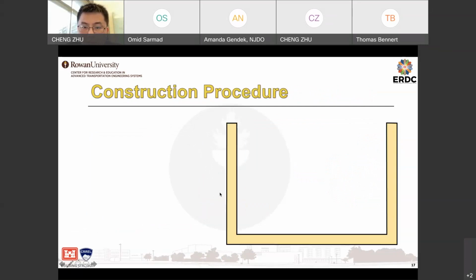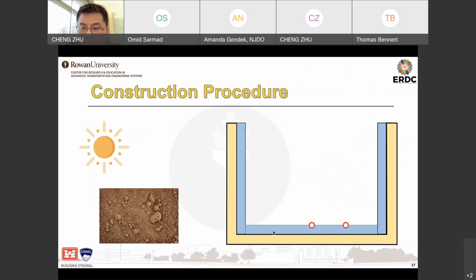First, we make this soil box, and we put the XPS board as the insulation layers, which are indicated by this blue color. And then we install those thermocouples to measure the temperature in the soil and the pavement section. The soil samples are initially wet, and then we dry the samples. We add the target amount of moisture to reach the optimal moisture content.